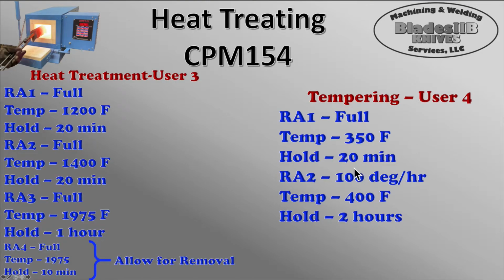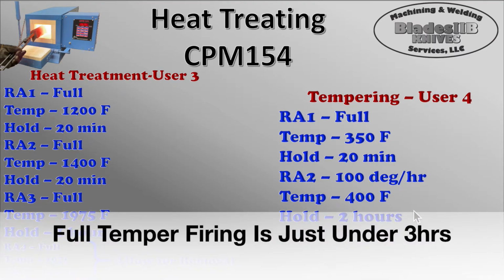And then we're going to slow that down and we're going to ramp up at 100 degrees per hour for the last up to 400 degrees. So it's going to take about 30 minutes or so to get up to temperature. And then we're going to hold that there for 2 hours for our tempering. And we're going to do this twice.